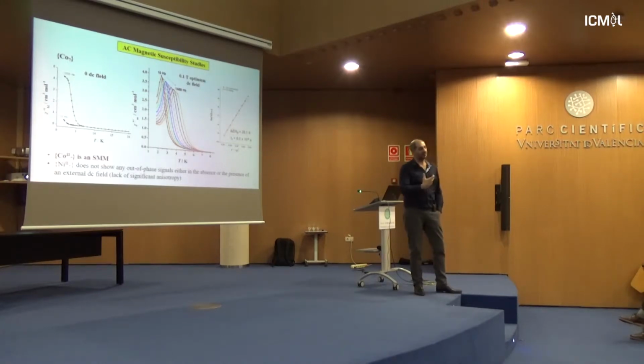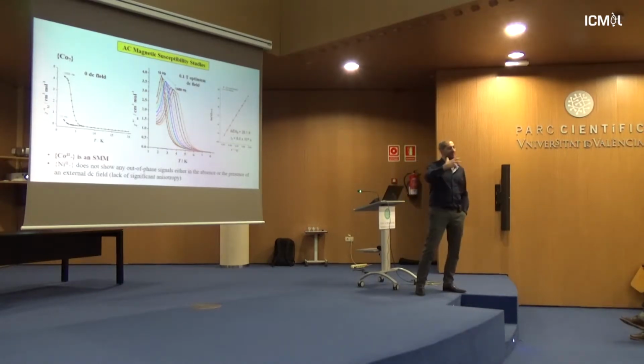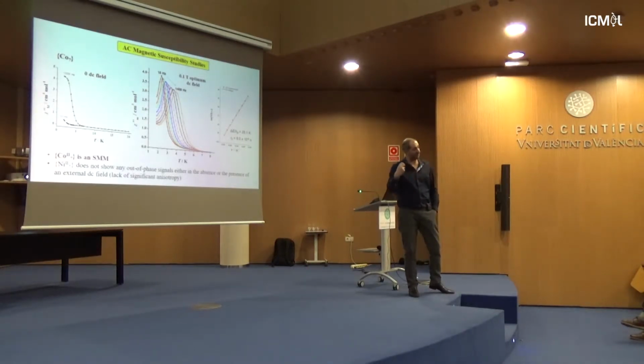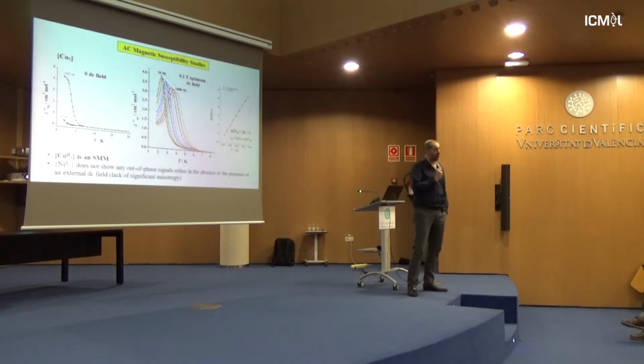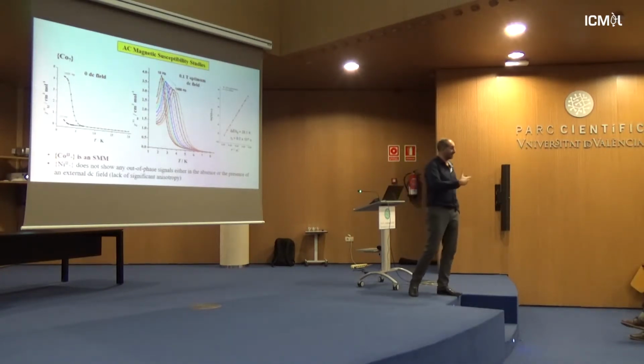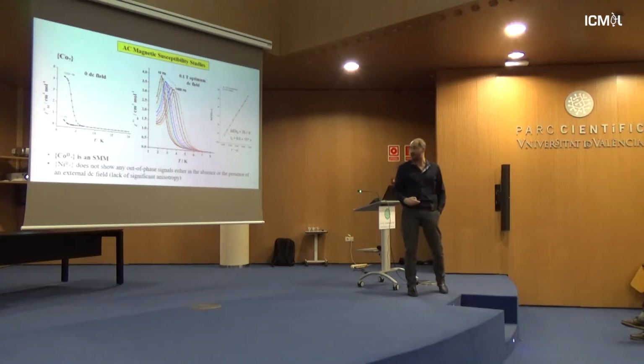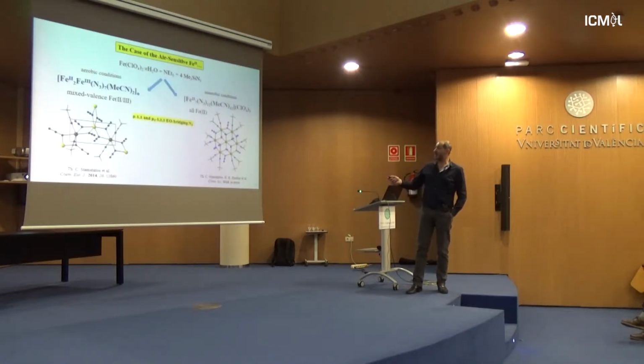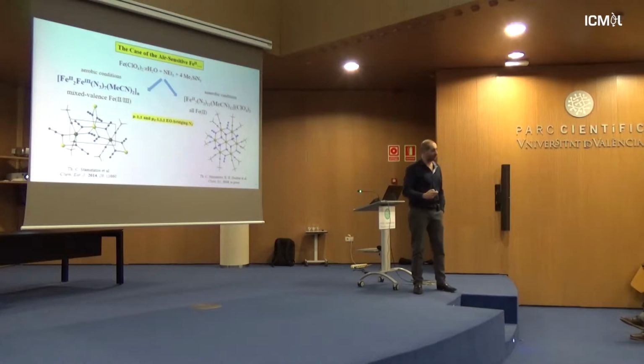So the purpose here is not to really solve a tremendously high energy barrier for single molecule magnets, but to try to convince you that this is a nice new route to high-spin molecules, giving you the maximum S values. The cobalt-7 and nickel-7 were the first compounds, so we tried really hard to expand this chemistry to other transition metal ions. The next metal ion that we tried to use was iron.